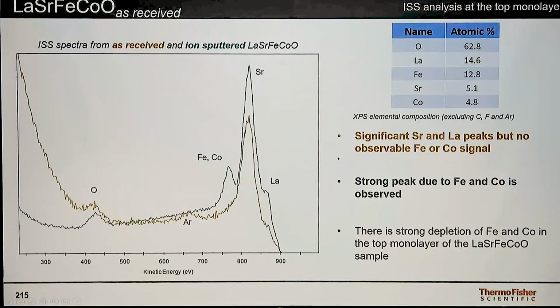Then we could do the ISS, because the XPS is telling us the quantification of the 20 to 30 atomic layers of the surface. But what we really want to know is what the outer layer is of the sample. And if we look at it before we've cleaned it with the ion source, so this is the as received, it's quite interesting. We see a little bit of argon in the surface. This is from the production process as they were depositing the material into the sample. So we see a very strong strontium signal and oxygen. And so the surface is strontium rich.